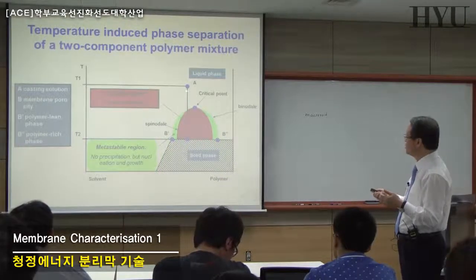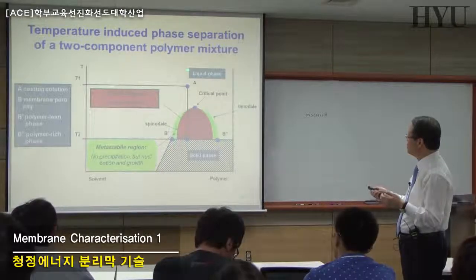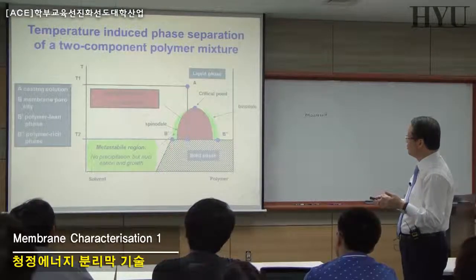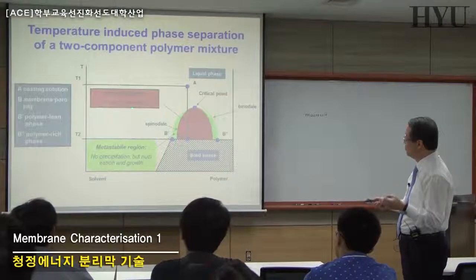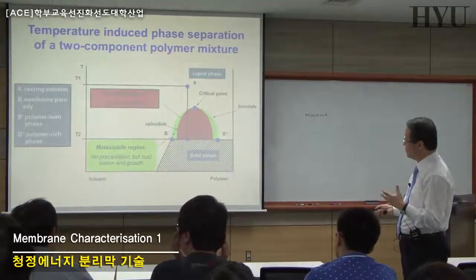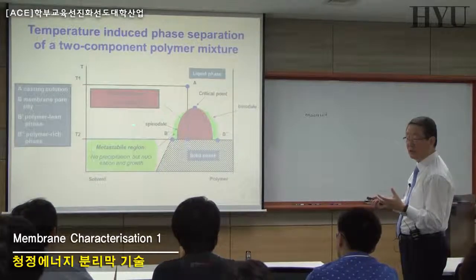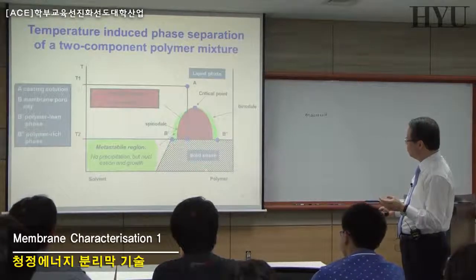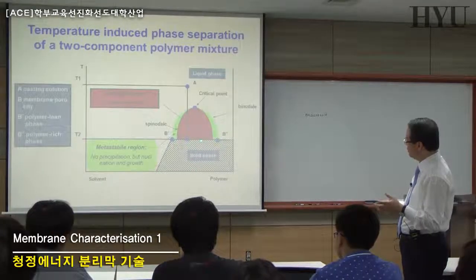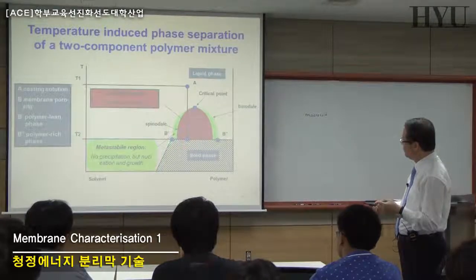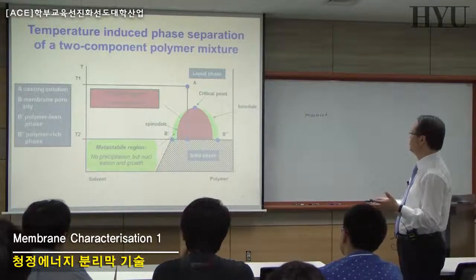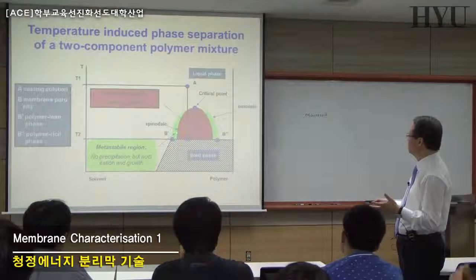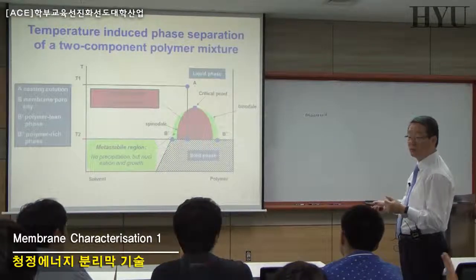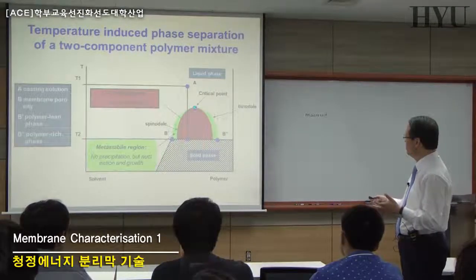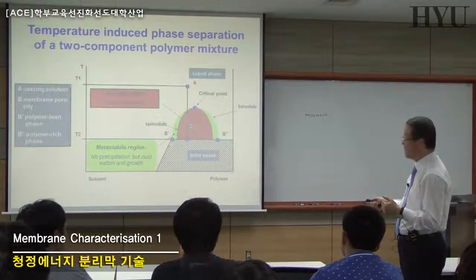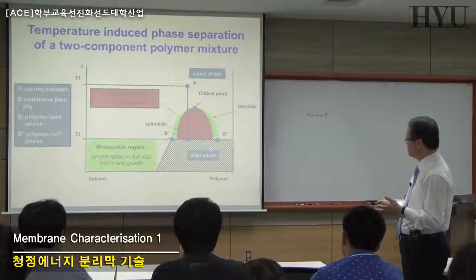Okay? So this is the phase. This white region is the liquid phase region. So you can make a solution, a liquid phase, at low polymer concentration very easily, whereas it's difficult to make a polymer solution at high polymer concentration regions. And you have the green region, the red region, and the black region here.